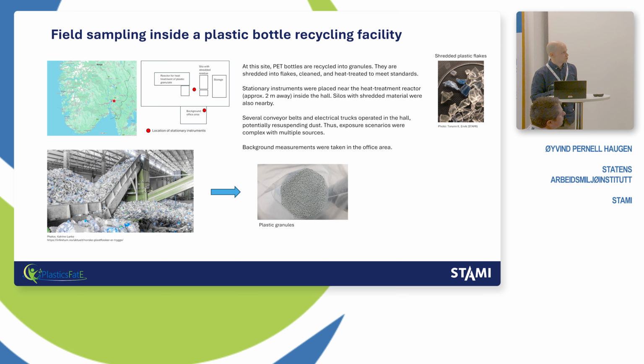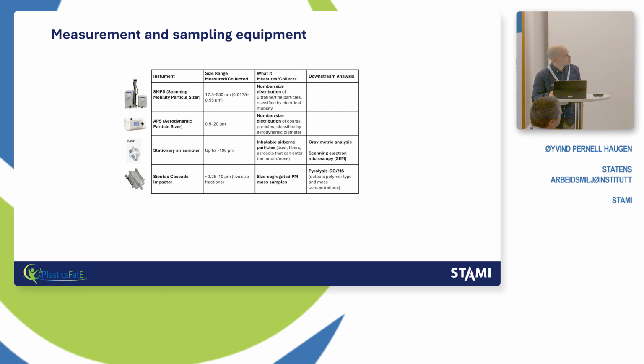And there are a lot of potential sources for the micro nanoplastics in here. You have the heat treatment of the plastic, silos with shredded materials, conveyor belts, and trucks operating inside. So a lot of dust can be generated and come from these different sources. The measurement and sampling equipment: scanning mobility particle sizers, which count the smallest particles in the nano-size range. And then the APS, the aerodynamic particle sizer, complements this instrument by measuring a bit larger particles.